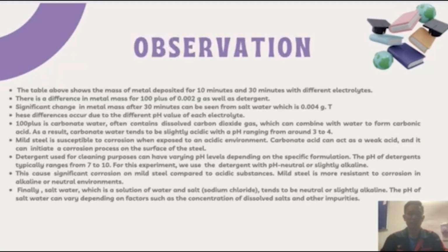For observation, the table below shows the mass of metal deposited for 10 minutes and 30 minutes with different electrolytes. There is a difference in metal mass for 100 Plus of 0.002 g, as well as detergent. A significant change in metal mass after 30 minutes can be seen from saltwater, which is 0.004 g. This difference occurs due to the different pH value of each electrolyte.